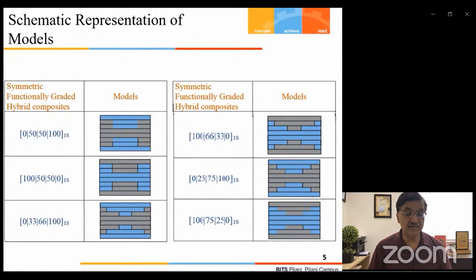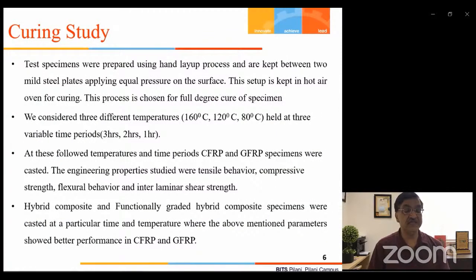In the same way, we can have different linear gradations for functionally graded composites. Curing has been done, and a particular schematic has been applied for curing the laminates. Three temperatures were selected: 160, 120, and 80 degrees centigrade, and curing periods of 3 hours, 2 hours, and 1 hour, to find the optimum curing duration for a particular temperature.